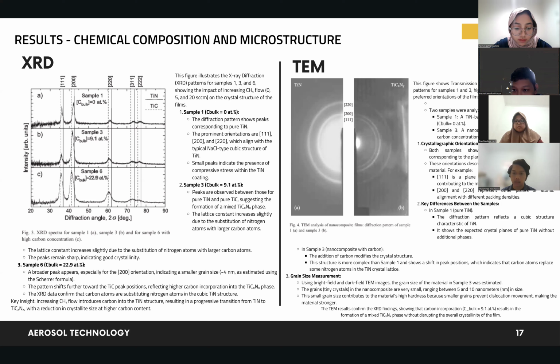In the TEM analysis, we can see that two samples are used, sample 1 and sample 3. From these findings, the carbon incorporation, which is the CH4 at 9.1%, results in the formation of mixed titanium carbonitride without disrupting the overall crystallinity of the film. Here we can see that the structure is more complex than in sample 1, and it shows a peak shift in position, which indicates that carbon atoms replace some nitrogen atoms in the TiN crystalline lattice.